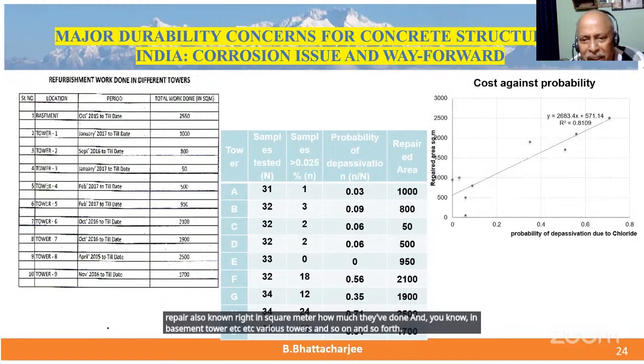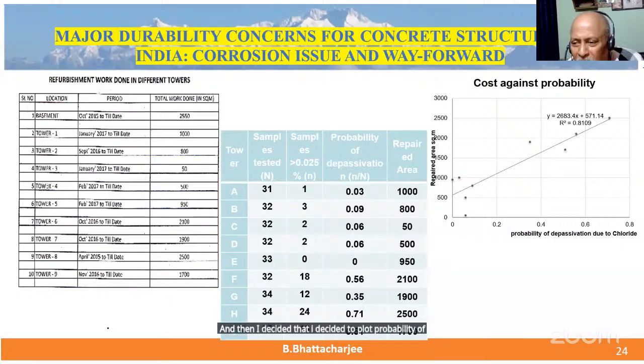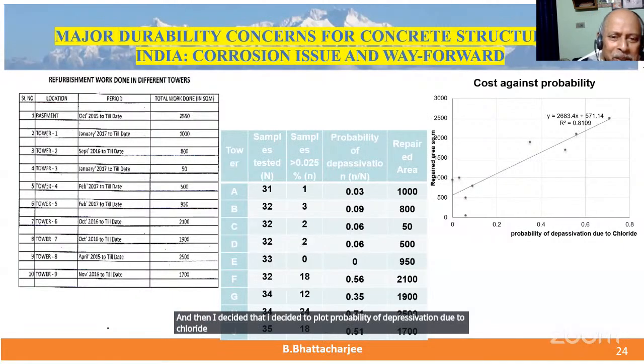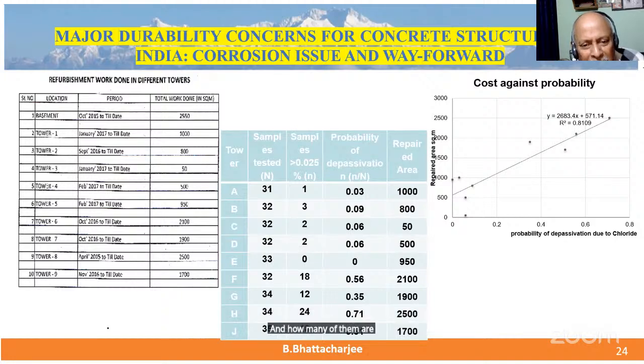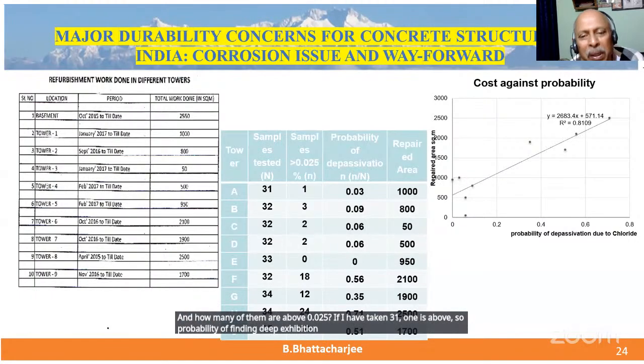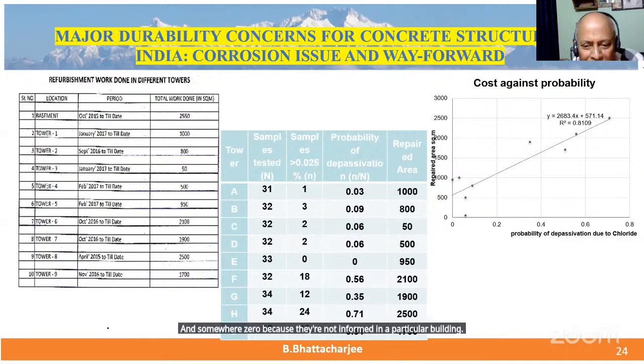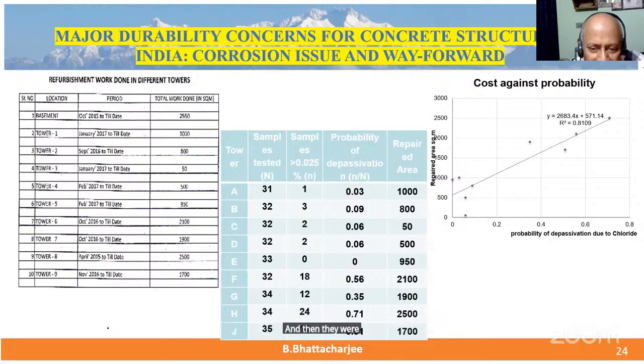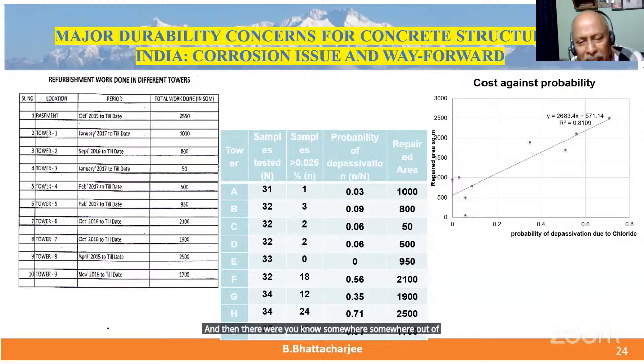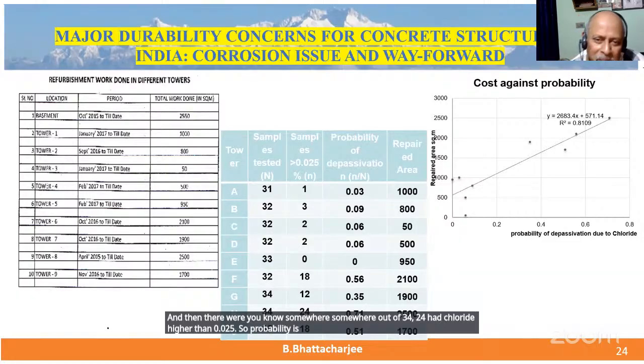And then I decided to plot probability of depassivation due to chloride, because probability of depassivation I could find out: how many samples taken from that particular case and how many of them are above 0.025. If I've taken 31, 1 is above, so probability of finding depassivation is 0.03, 1 divided by 31. And somewhere 0 because there are none found in a particular building. And then there were, somewhere out of 34, 24 had chloride higher than 0.025. So probability of depassivation I found 24 divided by 34, because that's how I had to